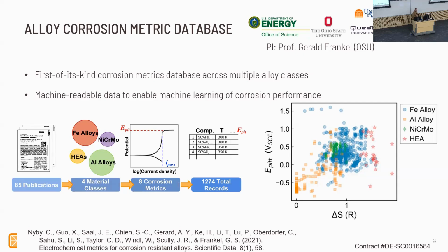So what nobody had done before is actually go in and scrape the literature, come up with a coherent data set of alloy corrosion metrics across different alloy classes. And so we did that as part of this project. And we came up with a machine learning ready data set to enable this kind of machine learning of this corrosion performance. So we looked at 85 publications, 4 materials classes, come up with over 1,000 data points.